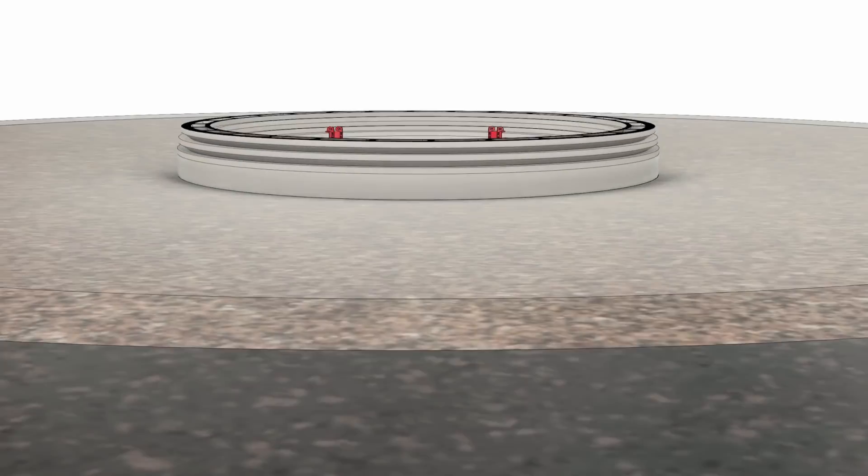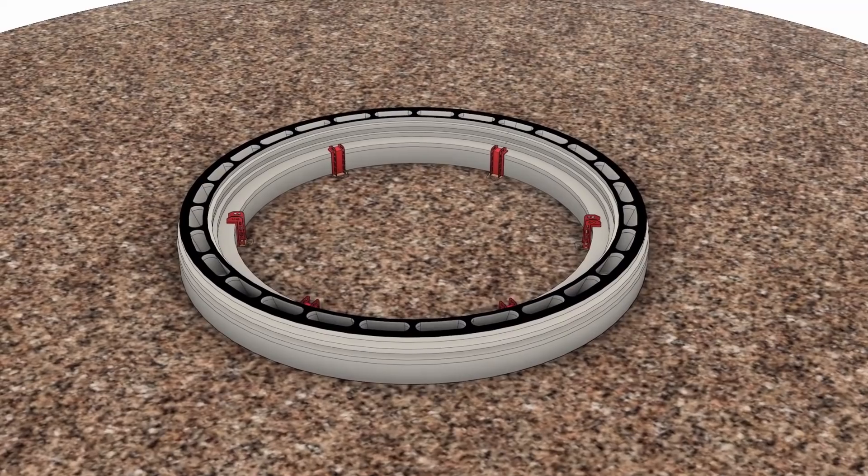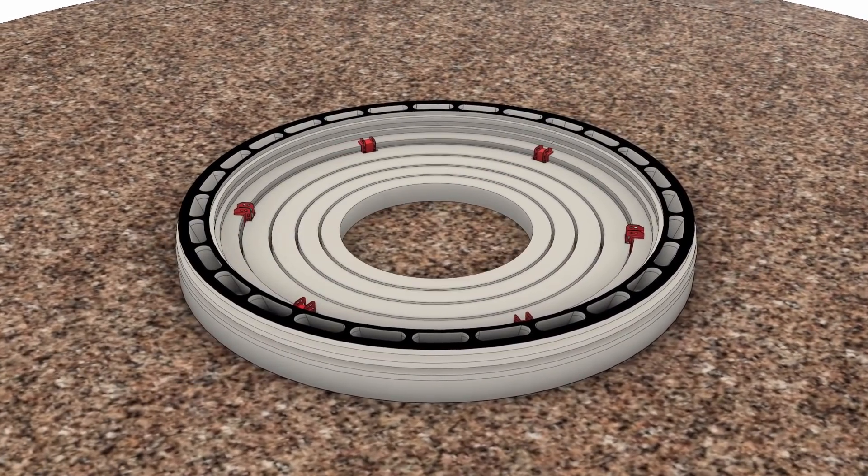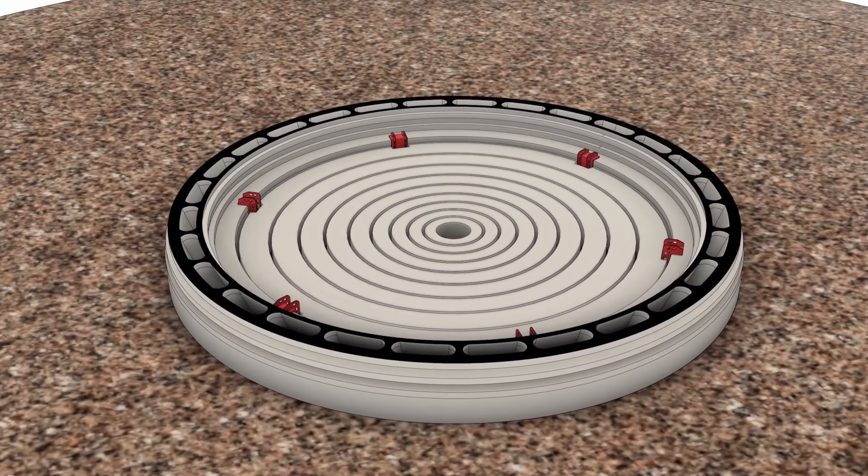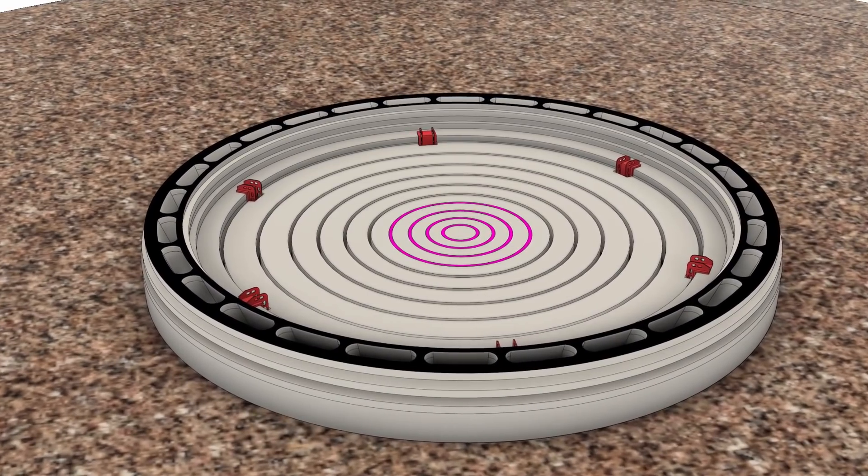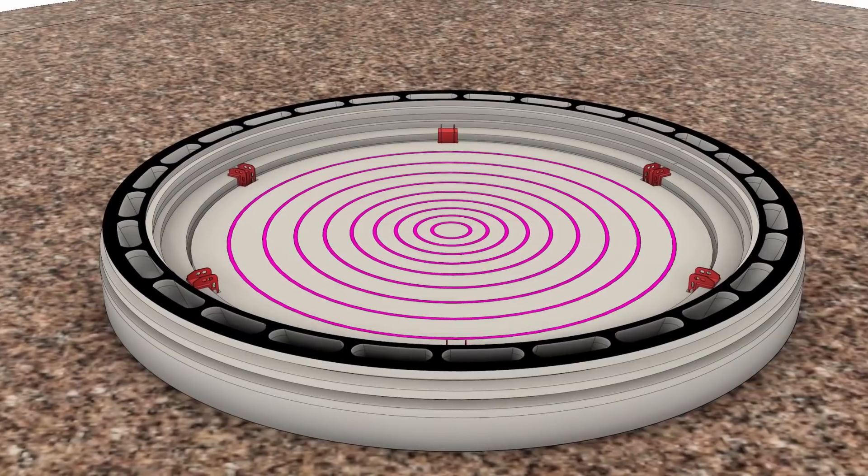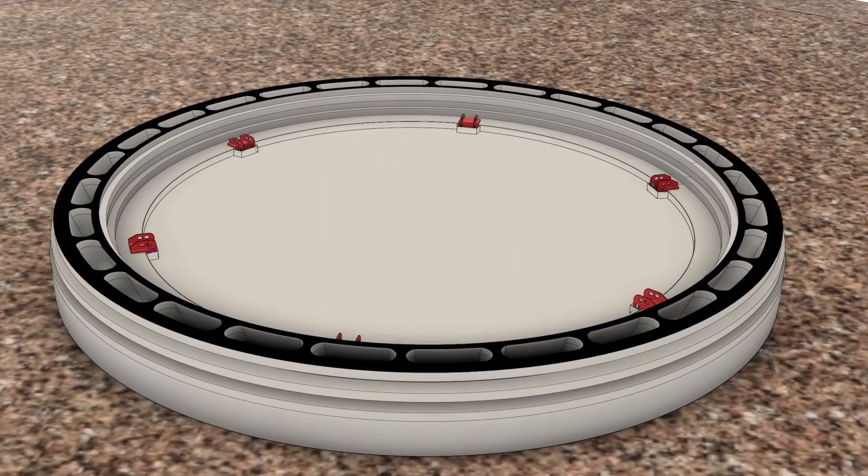In order to keep warping to a minimum, Marsha's foundation will be printed in concentric rings beginning from the outside. In contrast to full-area plates, rings would shrink predominantly in-plane, leaving predictable joints that can be backfilled without inducing shrinkage in the overall slab. With the anchors in place, a topping slab can be printed as a final seal without the risk of geometric distortion.